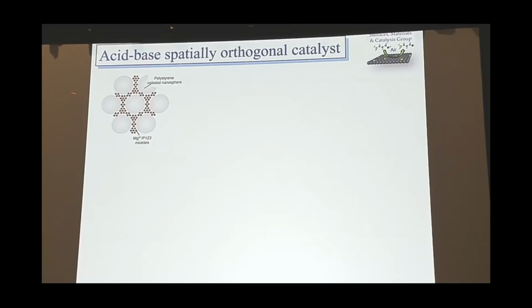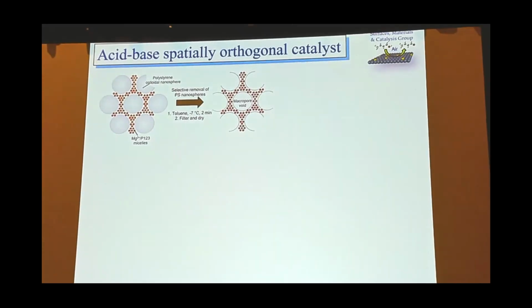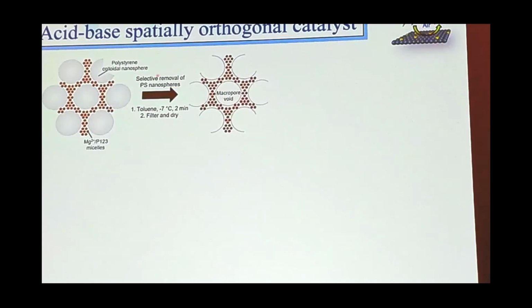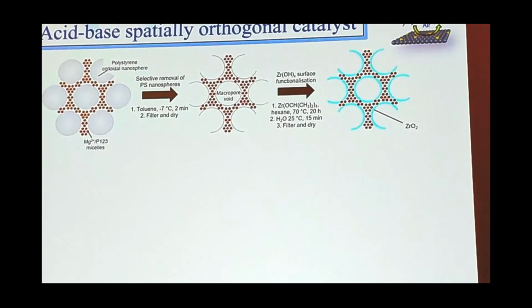All the materials I've talked about, though, we've burned all the templates out. We've not really been very smart with the design. And what we wondered is whether or not we can actually start to use these materials for acid sites that are spatially distributed, either in the macropore or in the mesopore. And so essentially, we modify the synthesis, and we start off with a Pluronic material that we've incorporated magnesium sites in. So we have a metallic surfactant that's Pluronic with magnesium, and then our polystyrene is fused. Then we remove polystyrene by refluxing the sample in toluene. So now we have vacant macropores and our mesopores that are full with magnesium doped Pluronic. What this means is we can now start functionalizing the macropores with a different functionality. So in this case, we put zirconia down by the grafting method we talked about at the start.